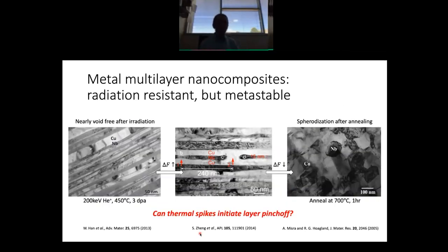In this one, I'll talk about metal multi-layer nanocomposites. So here is a TEM micrograph of a multi-layer of 2 metals, copper and niobium. These kinds of composite materials have been studied a lot over the past decade or two for a variety of reasons. They have a lot of very interesting properties, but one of them is that they're very highly radiation resistant. The reason is that when the layer thicknesses are very small, on the order of nanometers or maybe tens of nanometers, the area per unit volume of interfaces between the neighboring materials is very high.